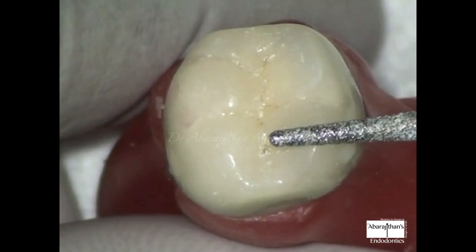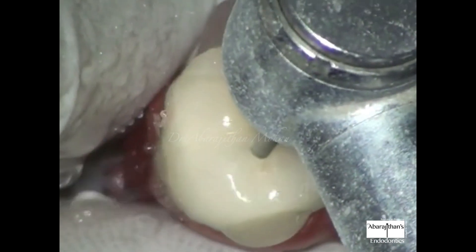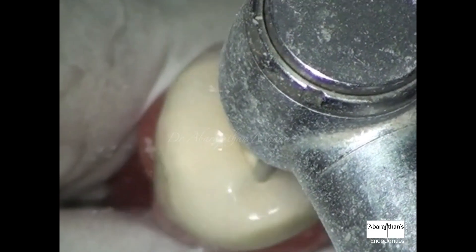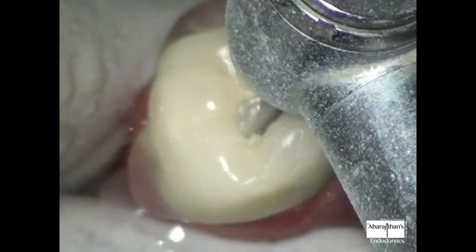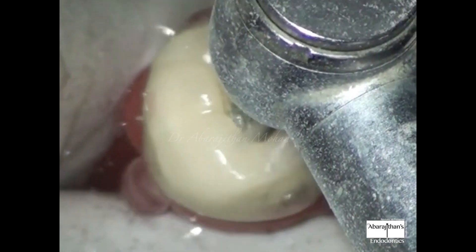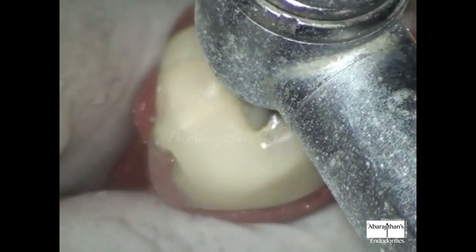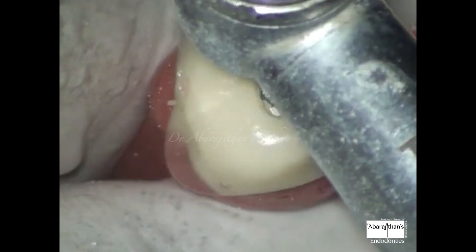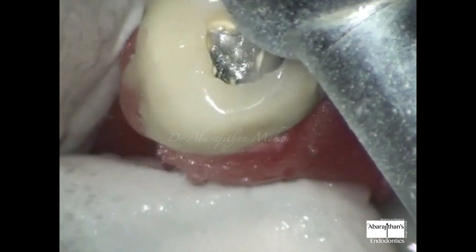Let's see an example: imagine you need to penetrate a metal-ceramic crown to create access or completely cut it to remove the crown. We are cutting two types of materials. It is not right practice to use a metal-cutting burr on ceramic, because TC burrs are not good for cutting brittle ceramic. When cutting ceramic, use a coarse diamond burr — prepare a tentative outline of the access and remove the ceramic part with a diamond point.